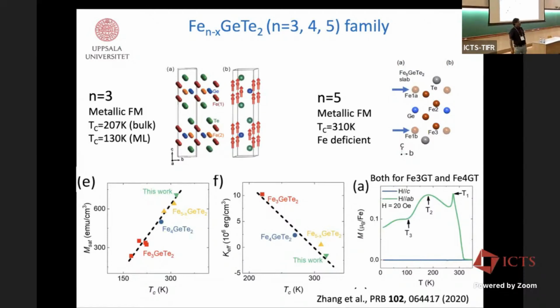Oh, gate, no. This is real substitutional doping. Okay, you are talking about the gating effect. That can also be simulated in our simulation, but you need to shift the Fermi level in a simple-minded way. This is metallic. No, ionic doping, people have seen that with the gating effect, but then they apply an electric field. Basically, it means that you shift the Fermi level with electron doping or hole doping, towards the right or towards the left. It is a rather simple thing.